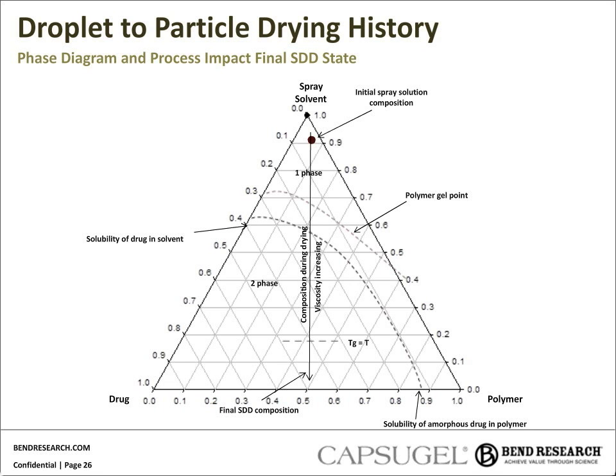It's important that, if at all possible, we try to cross the polymer gel point before we are supersaturating the API in the spray solution. That will limit the chances that we're going to have drug precipitating out in the droplet, which would lead to a heterogeneous SDD, and then make it very challenging to stabilize these or even be predictive about what the physical stability is going to be.